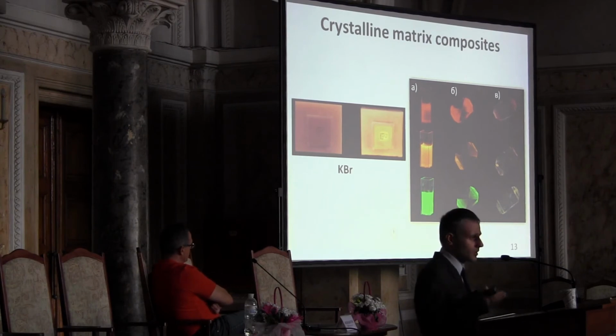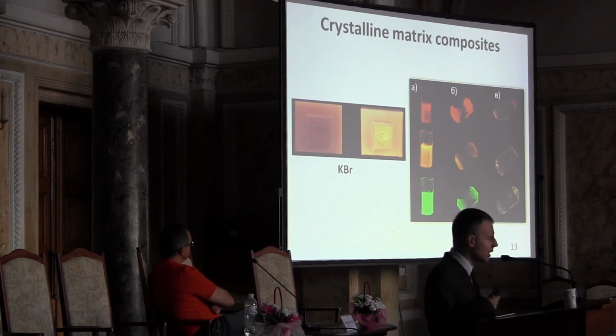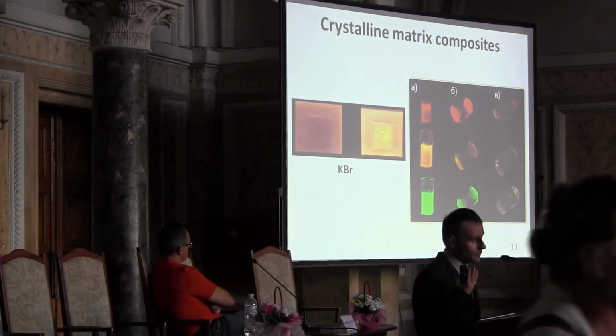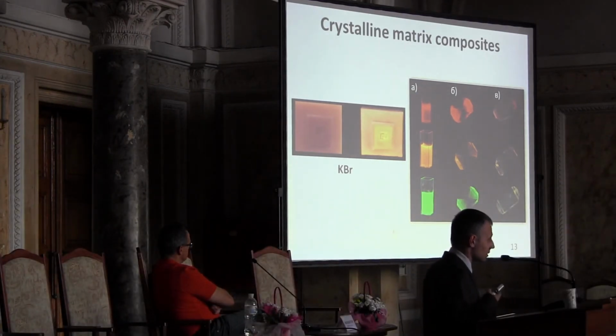Of course, they should be more or less chemically inert to the cadmium telluride, so it's usually either sodium bromide, potassium bromide, and so on. And if you leave it to evaporate, if you grow it, you can end up, in case of sodium bromide or potassium bromide, for example, with this kind of structures that are still preserving, as you see, the properties of quantum dots because they're embedded inside.